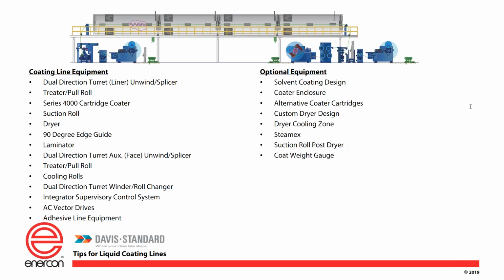You can do it with a roll method. You can do it with a shower spray. Steam is the most efficient way because steam particles can penetrate silicone coatings, whereas water cannot. And then you can also look at post-roll coating, such as another dryer pass or a suction roll at the end of the dryer to help you control the tensions. In longer dryers, you want a lower tension than on the rest of the machine. So if you put suction rolls front and back, you can actually lower the tensions in that dryer zone and control it better. And coat weight gauges. How much are we applying, so we know automatically instead of doing samples at the end of each roll.